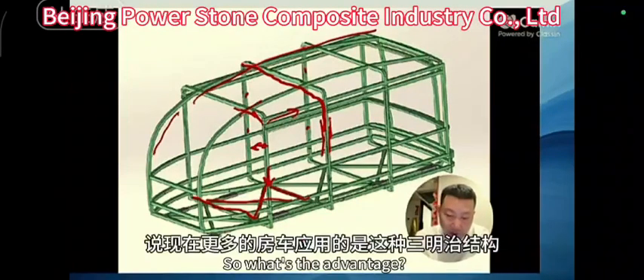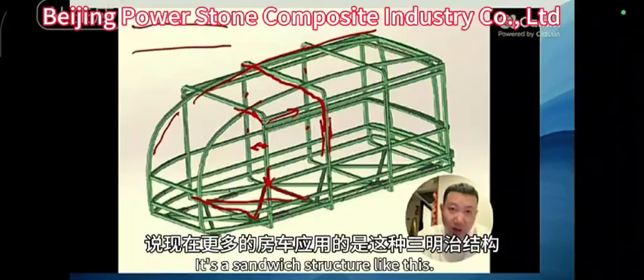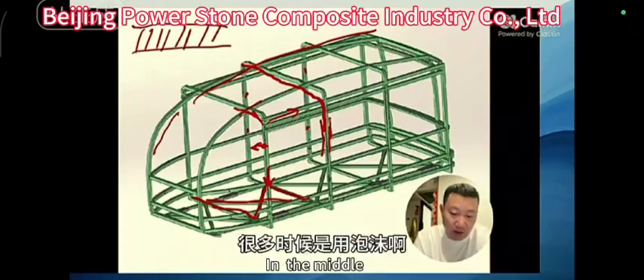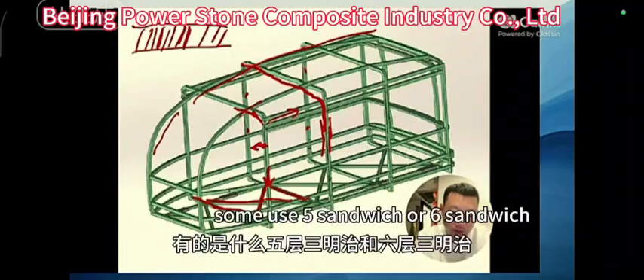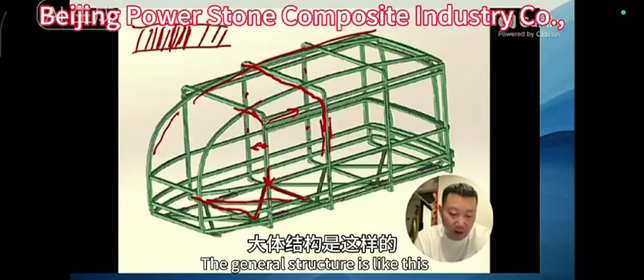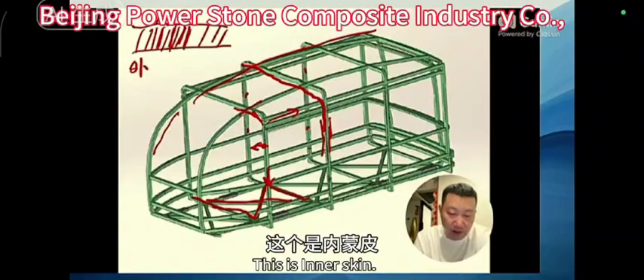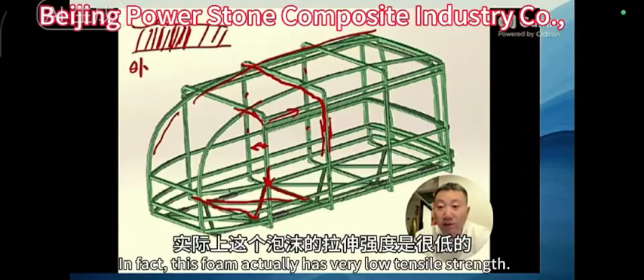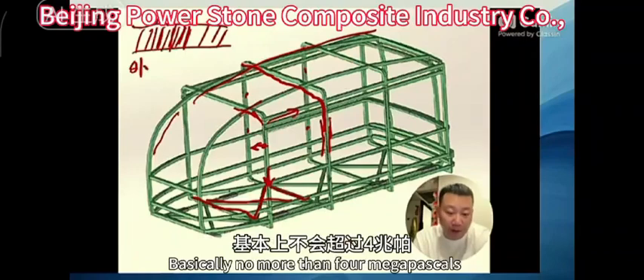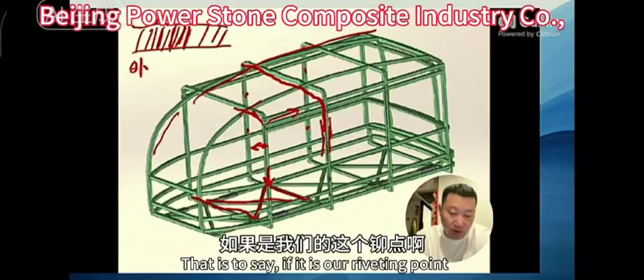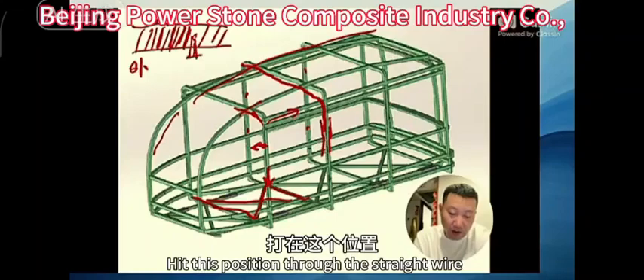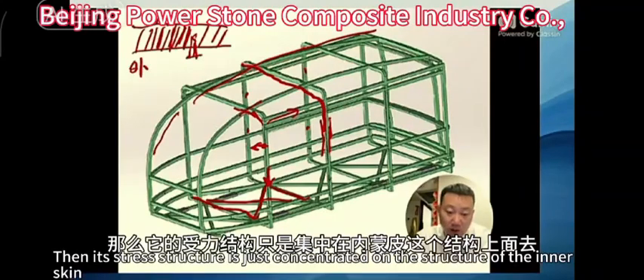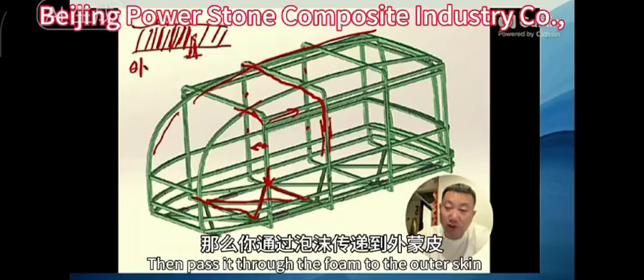So what are the benefits of this? Nowadays, more RV applications use this sandwich structure. In the middle is often foam. Some are 5-ply or 6-ply structures. The general structure is like this. This is the outer skin. This is the inner skin. In fact, this foam has very low tensile strength, basically not exceeding 4 megapascals. That is to say, if an anchor point is installed at this position, the stress-bearing structure will be concentrated on the inner skin structure. The force you transmit through the foam to the outer skin is limited.